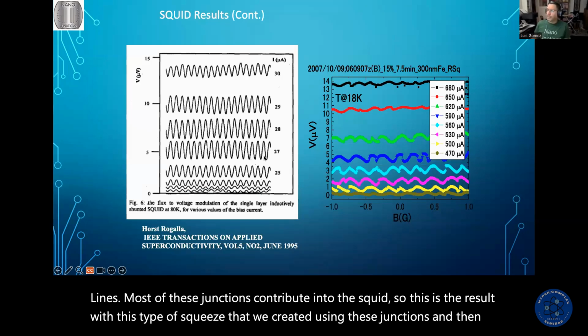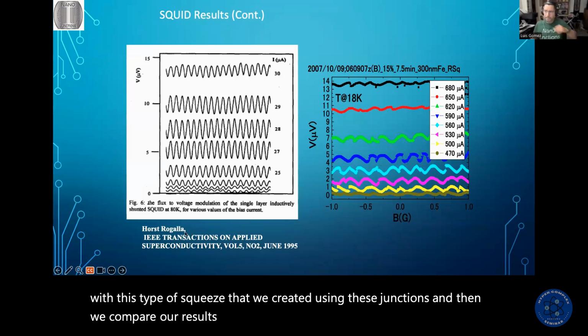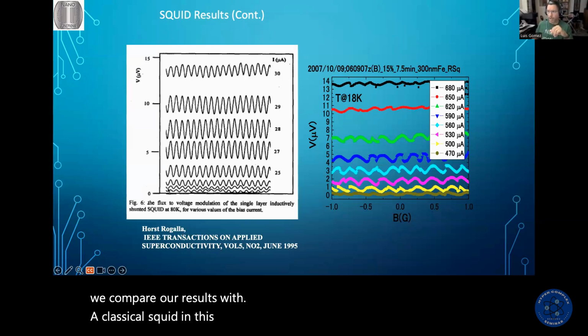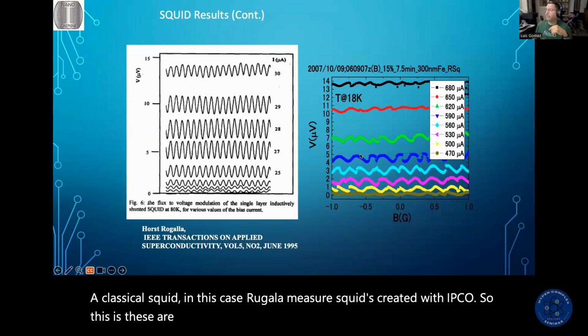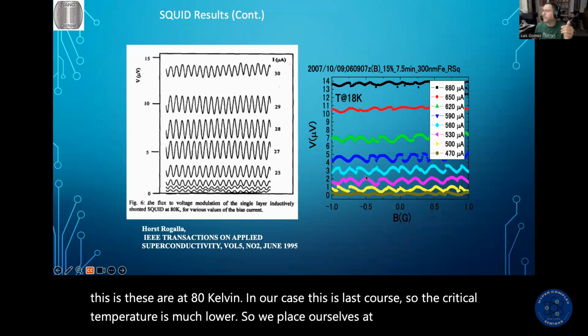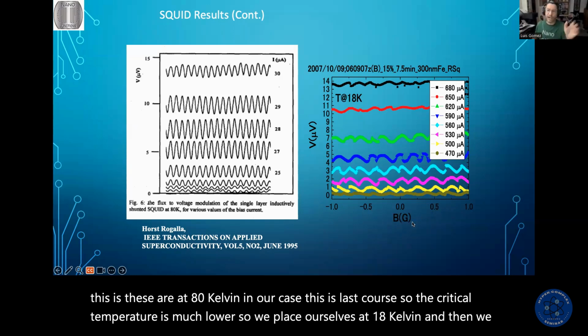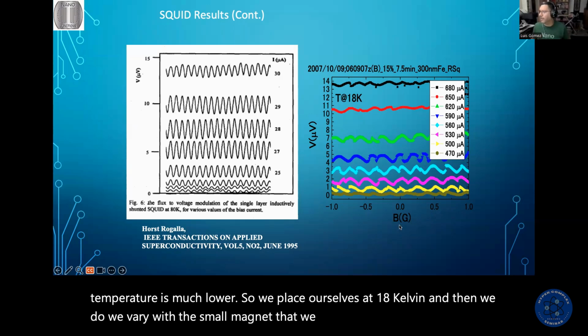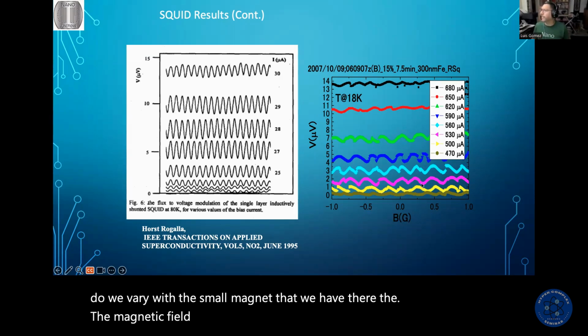And then we compare our results with a classical SQUID. In this case, Rogala measured SQUIDs created with YBCO, at 80 kelvins. In our case, this is LASCO, so the critical temperature is much lower. So we place ourselves at 18 kelvins, and then we vary the magnetic field with the small magnet that we have there, and we see oscillations as well.